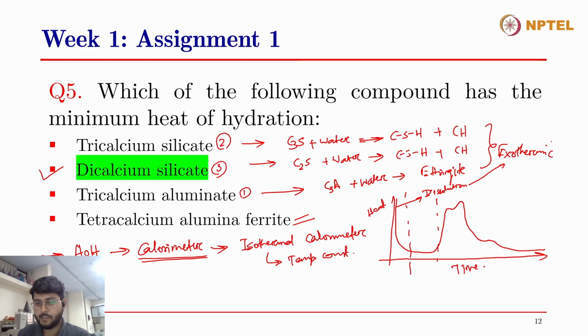The initial heat evolved is due to the dissolution. So the dissolution reaction is also exothermic in nature. So the first stage, there is a high heat burst, that is due to the dissolution. उसके बाद एक induction period होता है. In this induction period, the second phase, the heat is not completely zero, but there is some heat over there. Now, after the induction period, it starts accelerating.